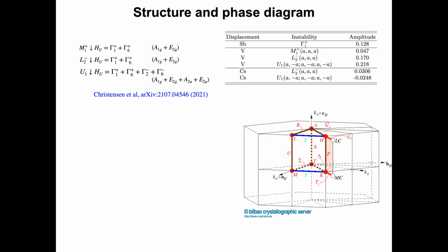Now, if we're folding M1, we have only this possibility. If the order parameter is L1, then it has an L2 minus mode, and we have this possibility, same as before. Technically speaking, if we are on this line in between, then there are 2 other representations, and those also break inversion. We can exclude that because we do not see broken inversion. By doing Raman spectroscopy, it's easy to identify broken inversion because infrared active modes will leak into the Raman spectra, and we don't see that.